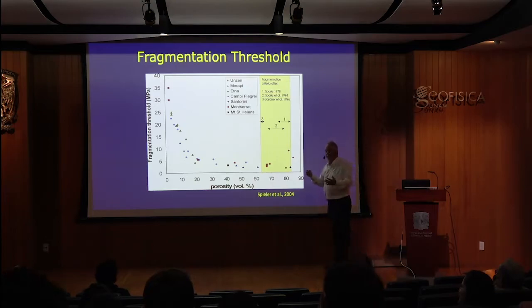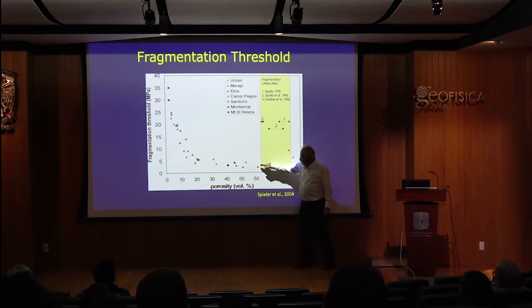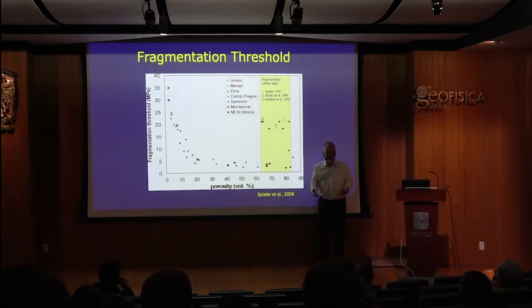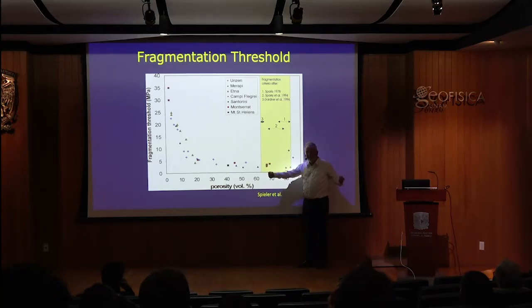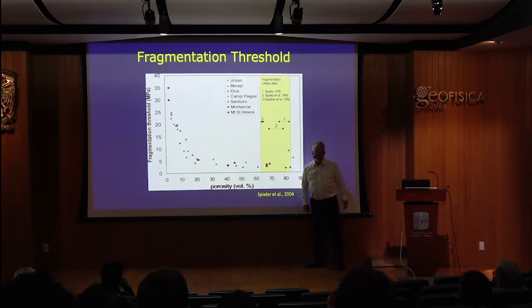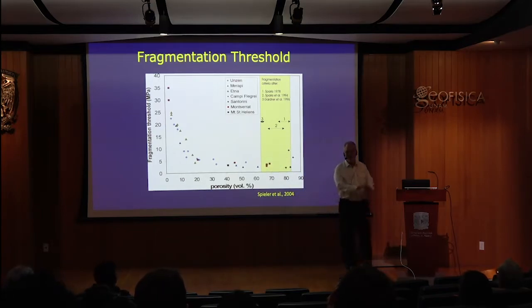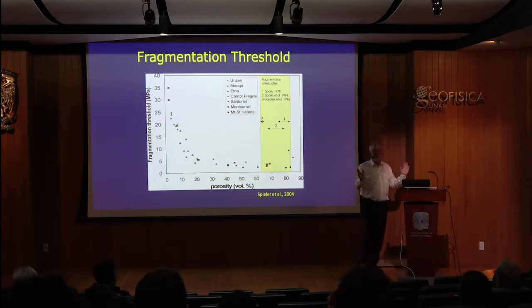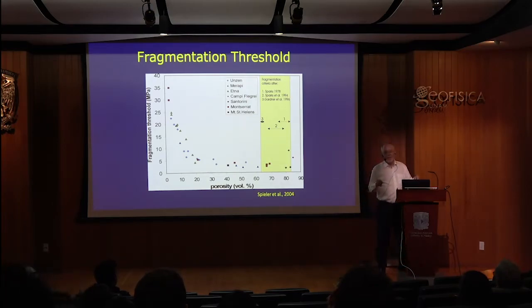How much does it take? How much pressure decrease do we need? It turns out to be a fairly small number. These magmas are very fragile. So if you look at a typical value of vesicularity, 60–70% vesicularity of bubble content in a magma, the strength of that against the tensile decompression is only about 3 megapascals, 30 bars. That's it. If you put a 50 bar decompression on a highly vesicular magma, you will destroy it and make ash.